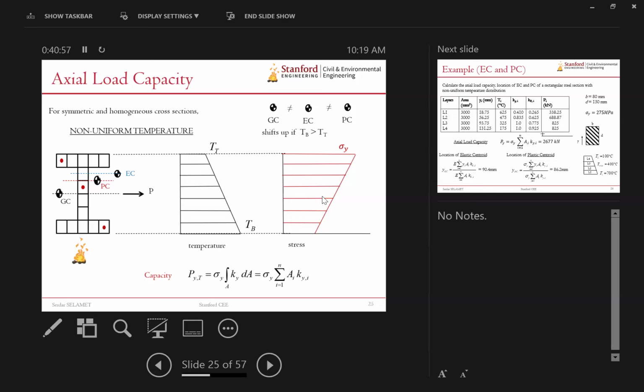So the geometric centroid is not changing throughout the entire analysis because you're not changing the cross section. But the elastic centroid, which has to do with Young's modulus reduction, as well as the plastic centroid, which is this here, is shifting up, not to the same location necessarily, because the reduction factors are different for stiffness and strength, but they are shifting up towards the cooler region, okay? And what does it do? It basically shifts this axial load either to the plastic centroid or elastic centroid, wherever you are in your analysis. So it actually induces additional moments in your cross section because the concentrated axial load will be acting at a different place than the geometric centroid.